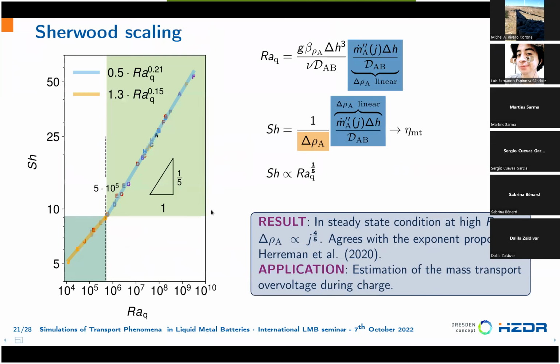Now we proceed with Sherwood scaling. As discussed before, the Sherwood scaling is really important for the mass transport overpotential. We find that all the results lie on this line in the high Rayleigh number regime, which corresponds to a 1/5 exponent. This 1/5 exponent corresponds to the concentration difference scaling with a 4/5 exponent of the current density. In this chart, we saw that it scales linearly with the current density. And this exponent agrees very well with the one proposed in Herreman et al. in 2020.